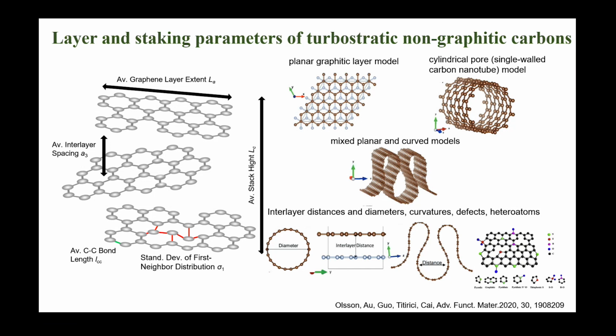We've been looking at how each of these parameters in the hard carbon, the average graphene layer, the interlayer spacing, the atomic distances, the curvatures, the pore diameter, the functional groups, are really affecting the sodium storage mechanism in these hard carbons.